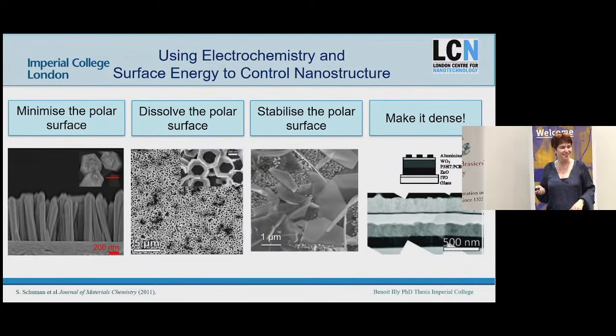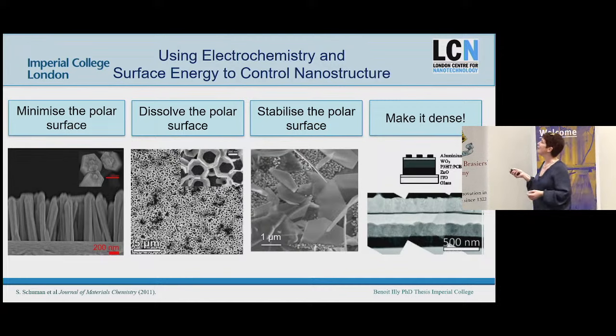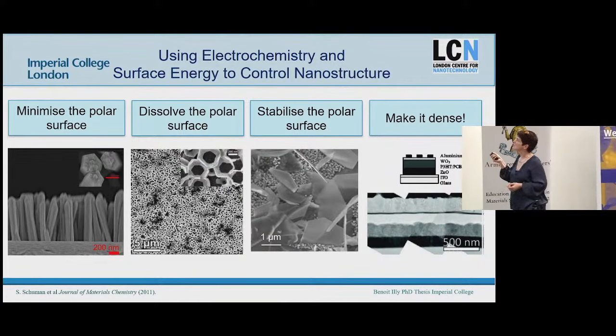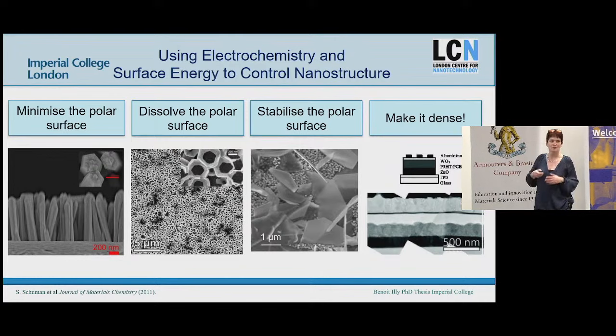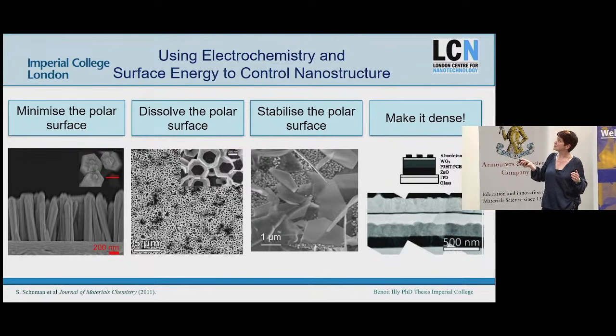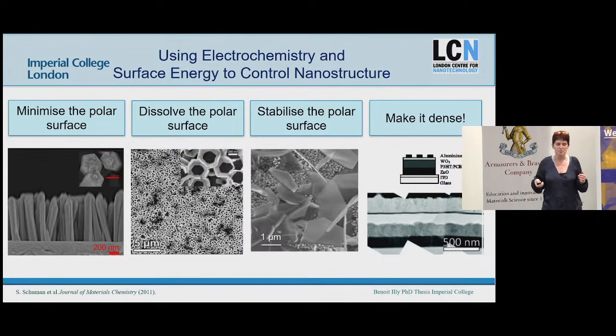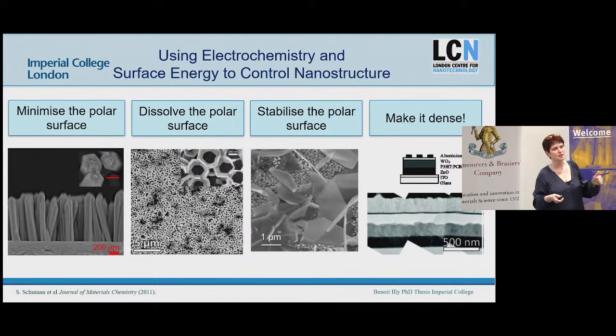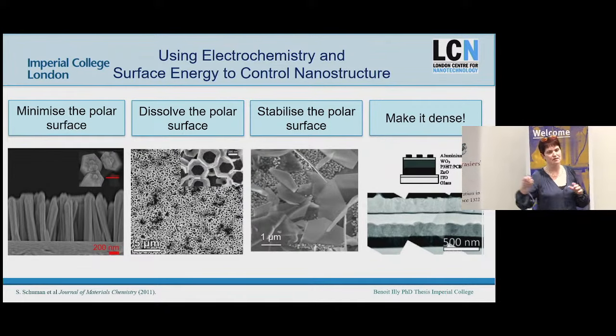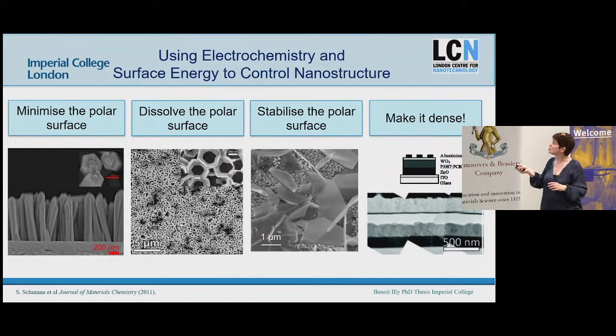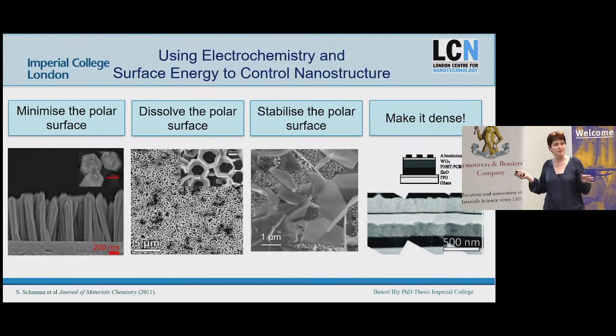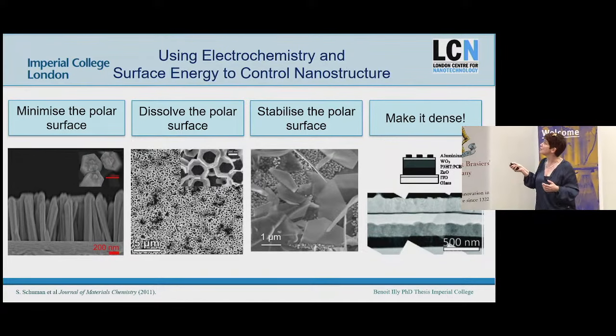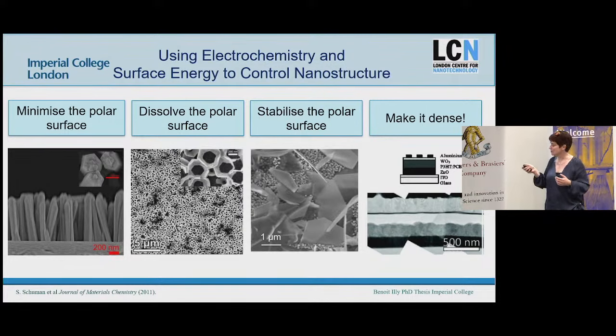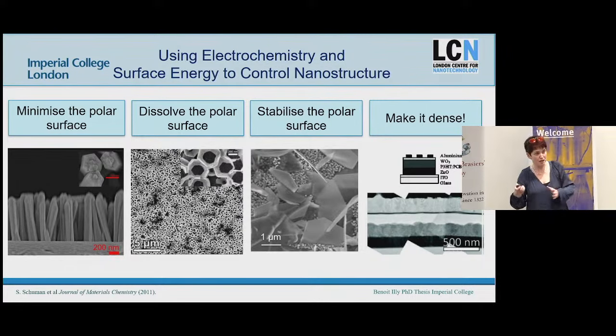And then this, it turns out, is the hardest one to do, making a dense film. This layer here is zinc oxide, electro-deposited. Normally, if you wanted to make a thin film of zinc oxide that was oriented, so this is all oriented in this direction, you can just about see where the rods might have been if it was growing. You would have to use a high temperature to crystallize it, a high vacuum system to deposit it. Very energy intensive. If you get the conditions right, you can grow it at about 50 degrees C in an aqueous solution with less than a volt. So energetically, this is much more stable, and you can do things like put it into these clever photovoltaics in a low energy fabrication way.